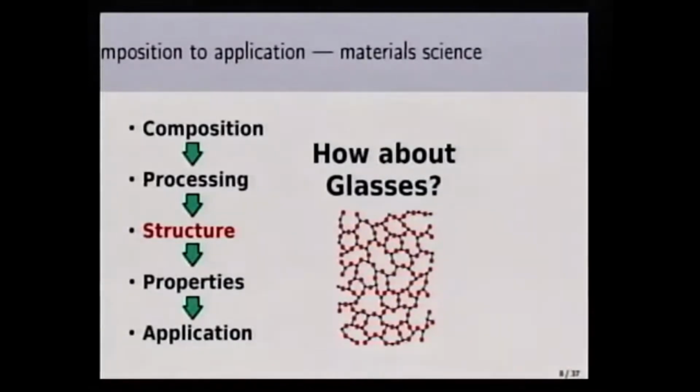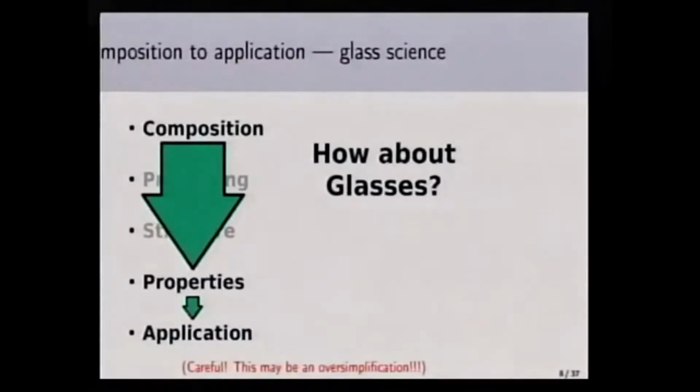You have other variables, but in the end, the distribution of structure that you can have is somewhat limited. What this means is that the properties of glasses are mostly dependent on the chemical structure. And we cannot say this of crystals, right? Because the crystallographic information of crystals will change a lot its properties. Think about carbon and diamond, right? Two materials with the same chemistry and wholly different properties. This is not the case for glasses. So we have this high dependence of the properties on the composition.